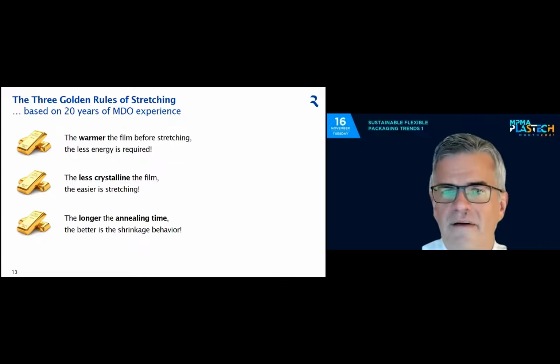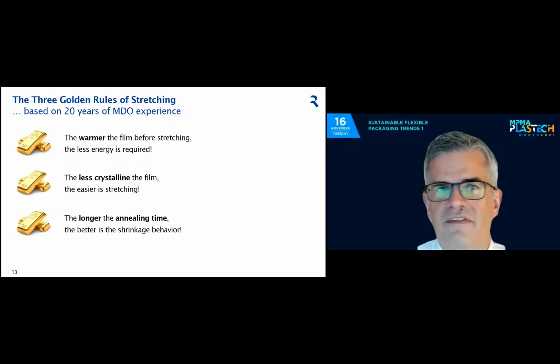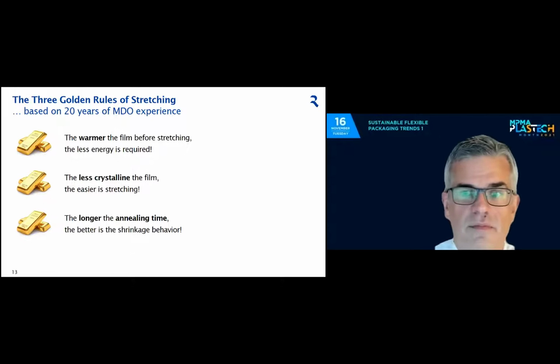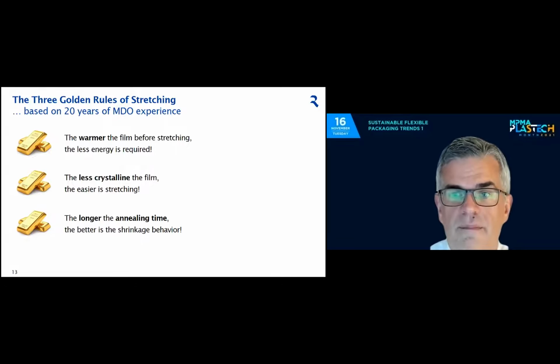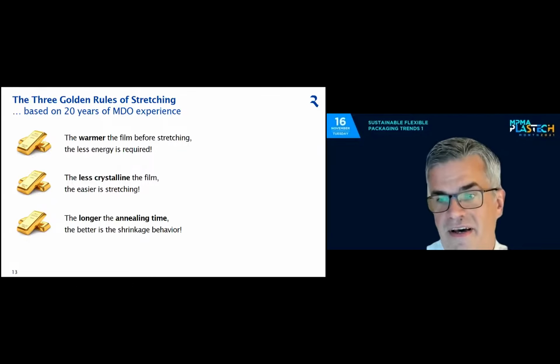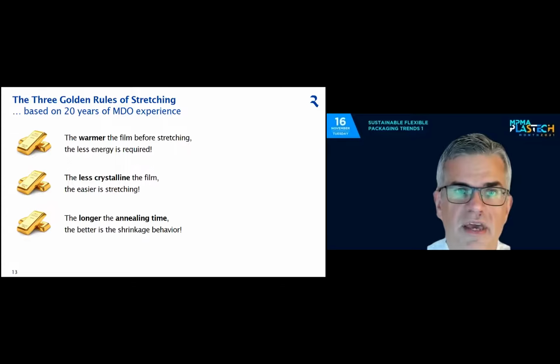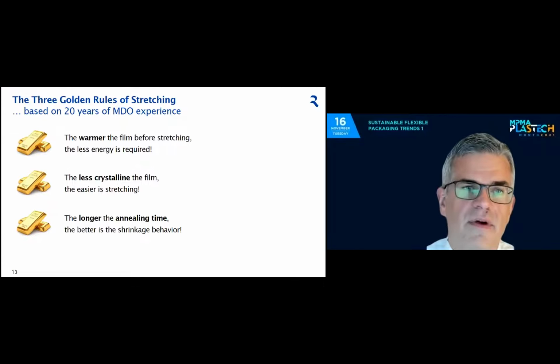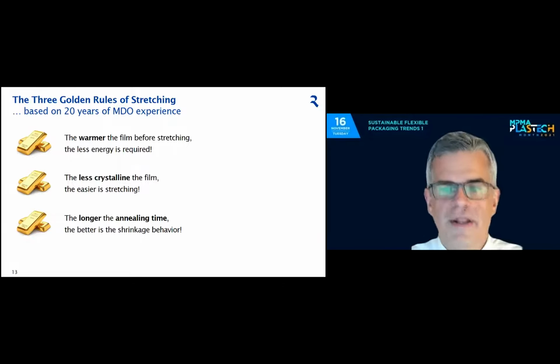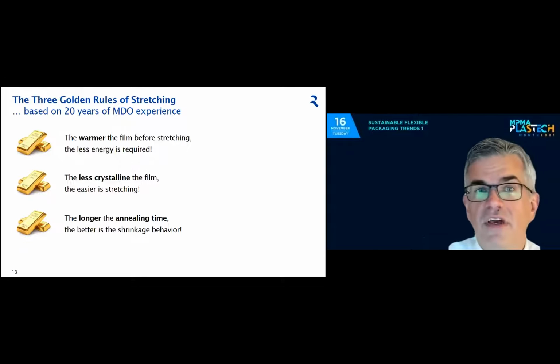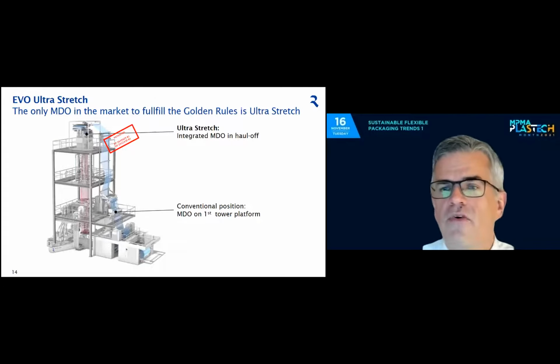And it is really worth thinking about the earliest position where I can do stretching in an MDO film. I will show you in only one slide where this position is in the blown film line. And the third rule, again important, is that the longer the annealing time, the better the shrinkage behavior. So give the film as much time as possible to anneal, to shrink, before you wind it up. Well, if you take these three rules into consideration and rethink what is the best position for an MDO,